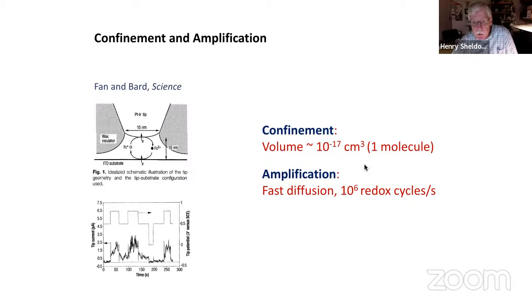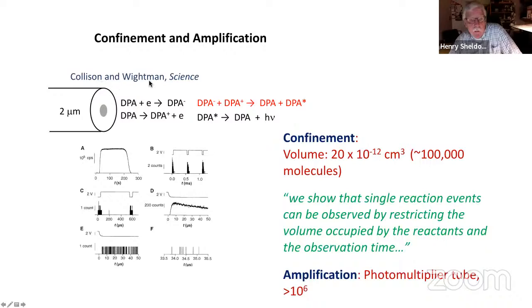Go back and look at these early experiments. The Fan, Fan and Bard experiment, well, the confinement part is bringing the tip down and isolating a single molecule. So there's only going to be one molecule. There could be two or there could be zero, but typically it's one molecule. They set this up so it's one molecule. And then the amplification results from the fast diffusion between the tip and the surface. And you get on the order of 1 million cycles per second, and that generates enough charge that you can measure a recorded current.